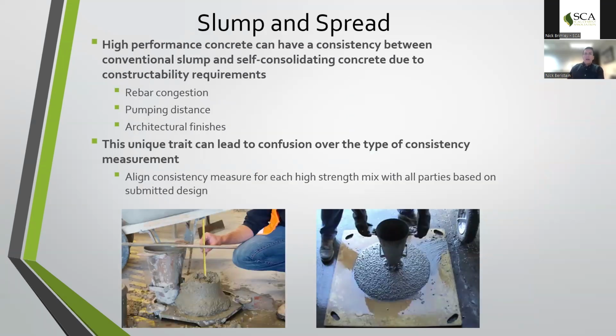As I mentioned a little bit earlier, some of the things that might help really both customers and expectations on the job site in terms of testers is a discussion on what type of consistency people request on site. If traditional slump is acceptable, slump is still a good measure. Again, most of these mix designs have superplasticizer in them in some cases. And so you can often achieve higher slumps with this with little to no change. 8-inch, 10-inch even can be achieved while maintaining submitted water cement ratios. And so if that is too rough of a gradation, switching to something like slump flow, or especially if you are running self-consolidating mix designs, can really help dial it in.